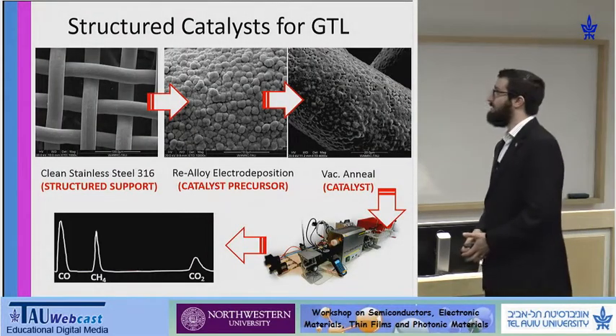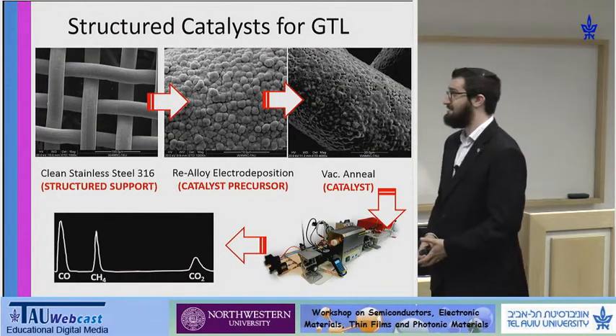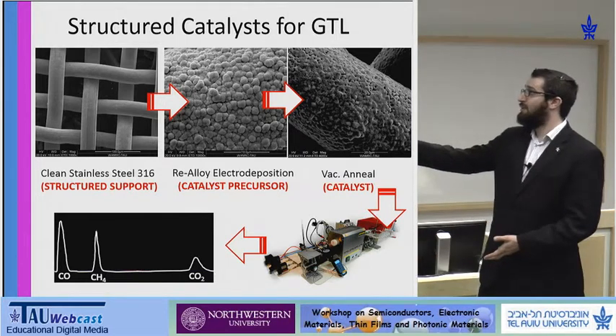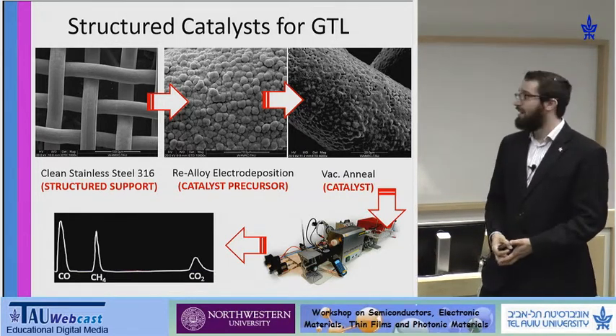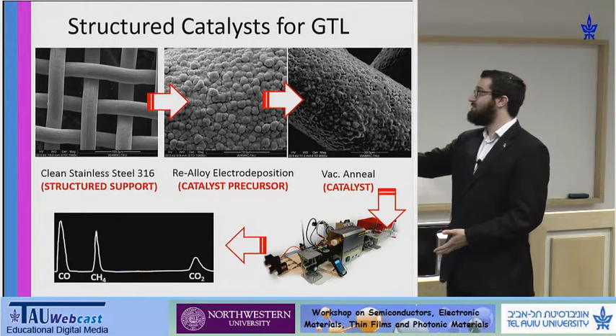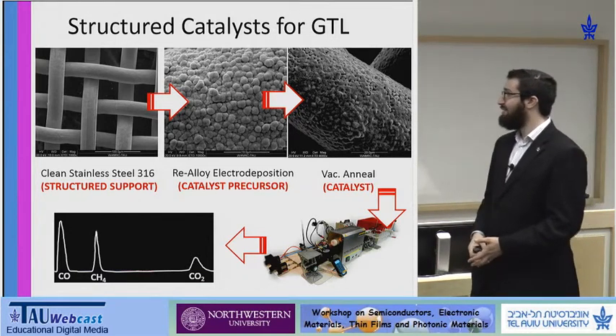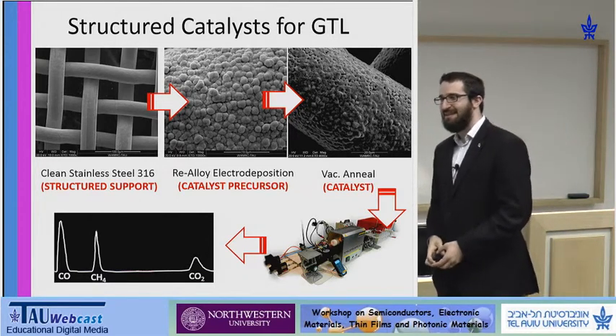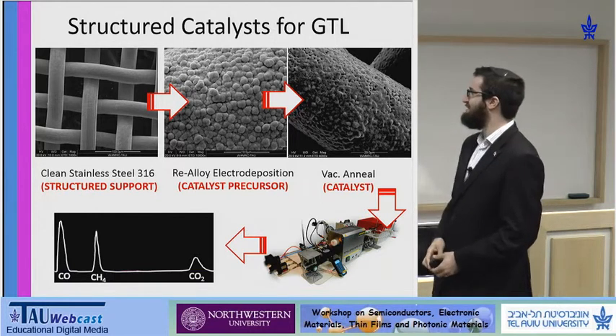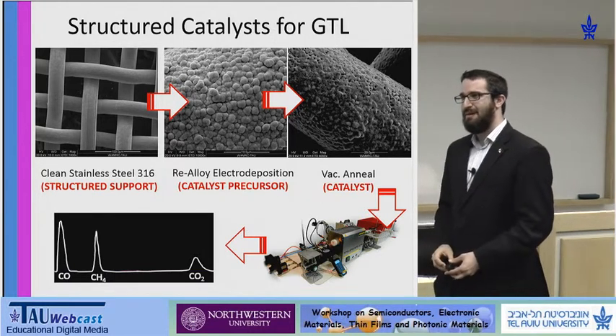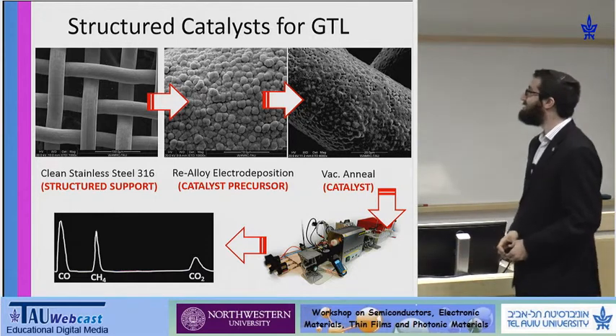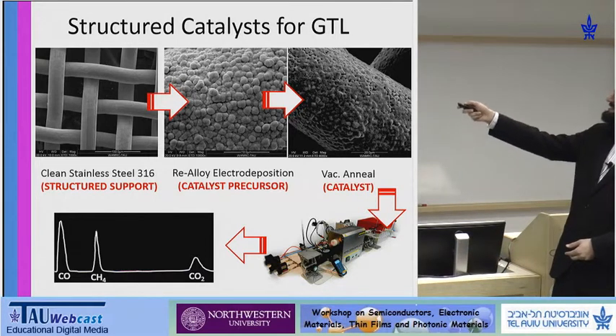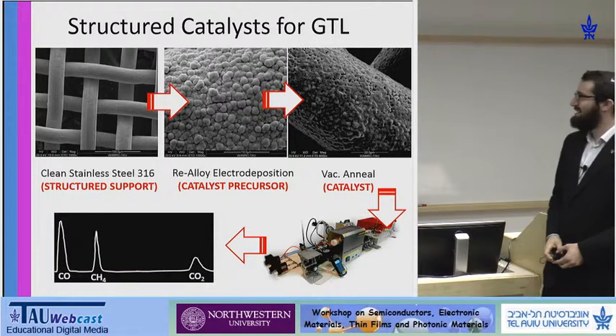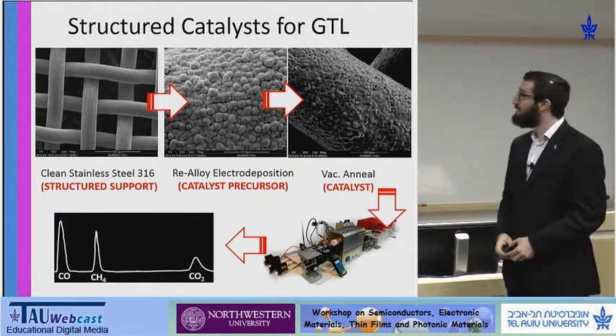So what we're looking at in our laboratory are structured catalysts. These catalysts have a support of a stainless steel mesh wire. And on this stainless steel mesh wire, we deposit a rhenium alloy. I'm calling it a rhenium alloy for the time being because the other elements of the alloy are still in publication, and we're keeping it hush-hush. So we have this rhenium alloy that's electrodeposited. This is not the active phase, rather a precursor.